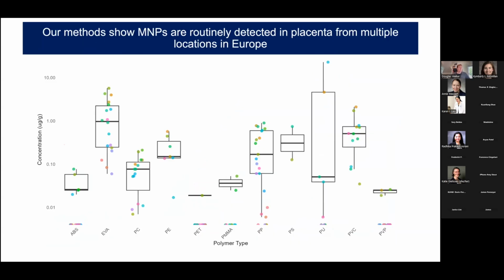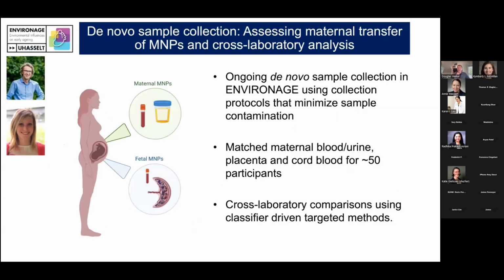And this is just some data from the microplastics methods, showing that we can essentially measure a range of polymers in placentas. And we're finding that the majority of placentas we're characterizing have at least one microplastic detectable in them, if not more. But we're also trying to develop foundational studies that tell us more about both this in utero exposure as well as maternal transfer of microplastics.